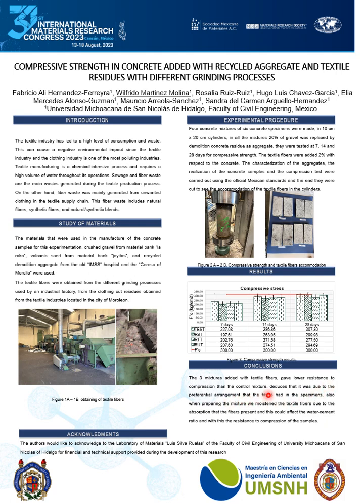We deduce that it was due to the preferential arrangement that the fibers had in the specimen. Also, when preparing the mixture, we moistened the textile fibers due to the absorption that the fibers present, and this could affect the water-cement ratio, and with this the compressive strength of the samples. Finally,